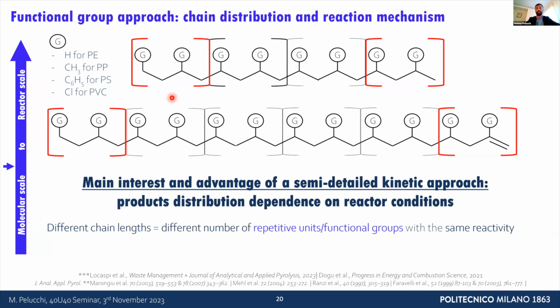These cover between C20 and C40 in terms of size of the molecule. Why C20, C40? Because if you think about heating up a polymer, it cracks, and if you form a species that has roughly a carbon number of 40 or below, this species at those temperatures will probably evaporate in the gas phase. So we need to track that species' evolution in the gas phase by connecting it to our gas phase model.